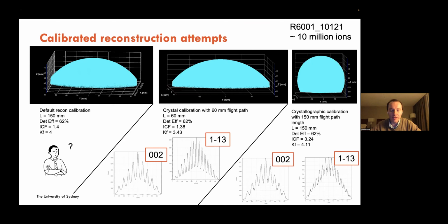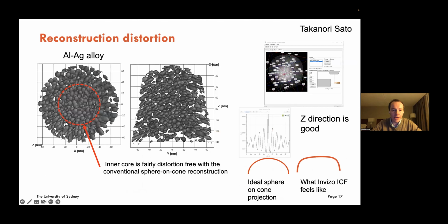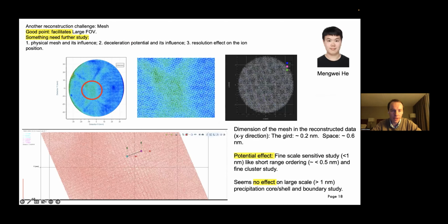But the default reconstruction parameters seem to be giving us a reasonable reconstruction. As Levi pointed out, there are some distortions out towards the periphery of the tip, which we're going to need to correct with better reconstruction protocols. And this Einzel lens is really awesome for giving us the larger field of view, but we are actually seeing this come through on the detector map and then also into the reconstruction. And there are questions over what that's doing to the fine interatomic relationships there.